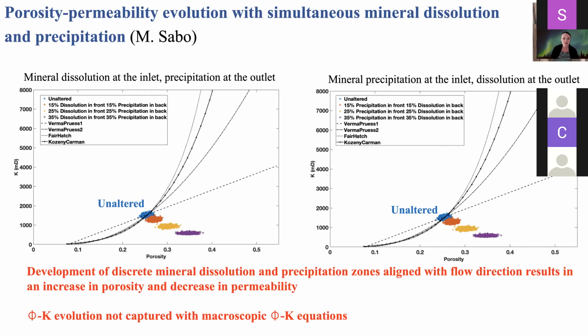We're currently trying to understand porosity permeability evolution in systems where you have simultaneous mineral dissolution and precipitation. So in the results I showed you, either dissolution or precipitation was happening, but in some cases you have both of those happening at the same time. And so this is work that my current undergraduate researcher, Molly Sabo, is doing. And in these simulation results, she's looking at what if you have a zone where mineral dissolution occurs and mineral precipitation occurs that is aligned or perpendicular with the flow direction, and looking at various extents of those reactions.